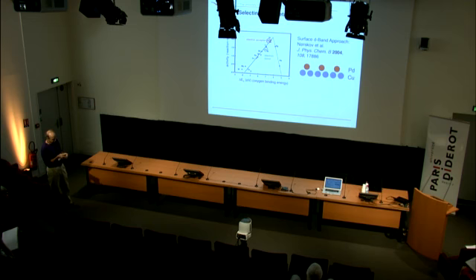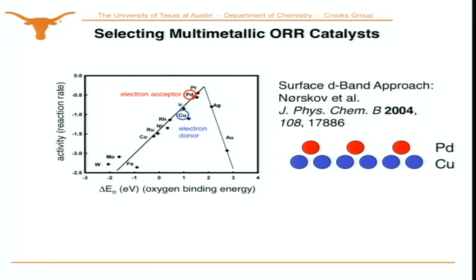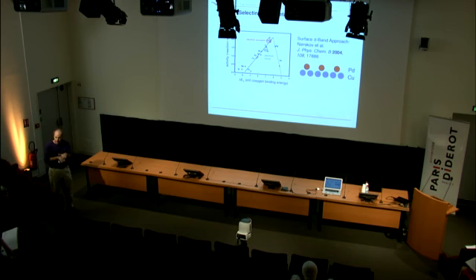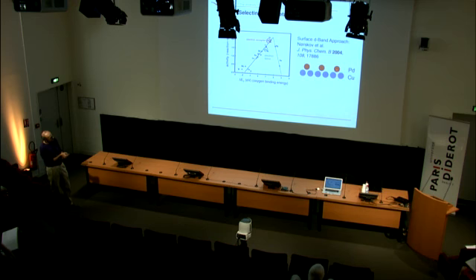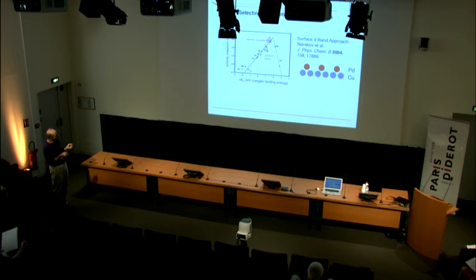So what Norskov suggested was building these things he calls near-surface alloys. So now what we're going to do is take another metal like palladium and a second metal like copper, which is an electron donor, and build an infinite two-dimensional surface. So the bottom layer is going to now donate electrons up into the d orbital of the palladium. It's the d orbitals that matter for oxygen reduction. It's these oriented orbitals with localized electrons that are going to have to get up into that oxygen in order to break the dioxygen bond. The free electrons don't matter. It's the d electrons. And so by putting this donor down here, it's going to make palladium look more like platinum. In fact, maybe even push it up here a little closer to the very top.